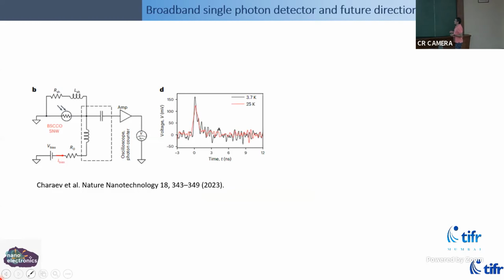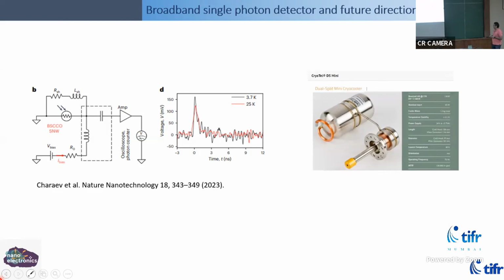A few months after our work, a group at MIT showed devices made by cutting this high temperature superconductor with a focused ion beam. Their devices are similar, but they can only operate up to 25 Kelvin, and they demonstrated single photon detectors. So at least the proof of concept using this idea works at temperatures above 20 Kelvin, which is the reason why we now want to double down and invest more energy in developing electronics which will allow us to do things at 60 Kelvin. That's our target.